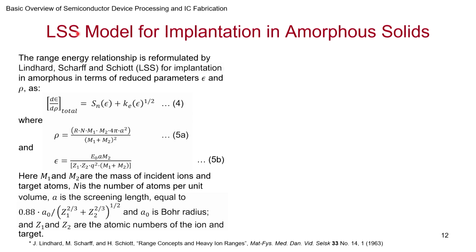LSS stands for Lindhard, Scharff, and Schiott, right? So, they are assuming that the ion is implanted in an amorphous medium, and what they have done is the electronic stopping, they have just replaced it by Ke times E to the power half, that is, as we saw, proportional to the velocity, and S_n is actually more involved.